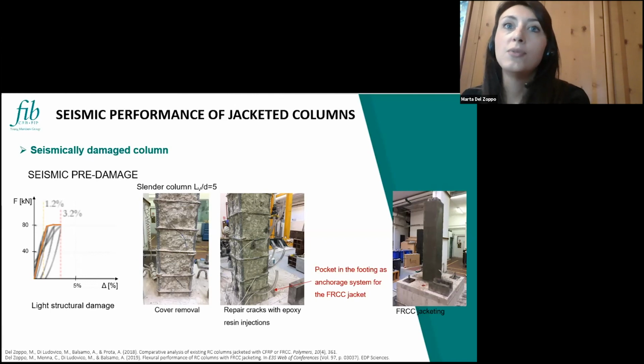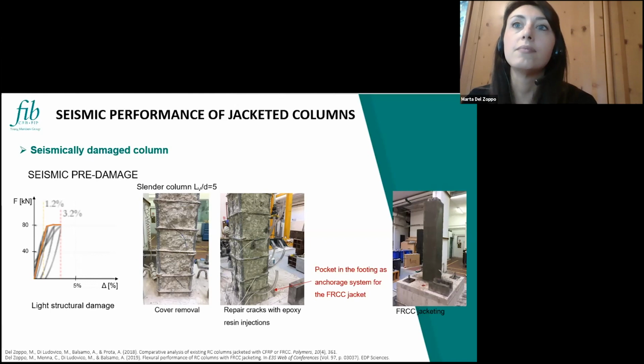So we removed the concrete cover, we repaired the cracks with the epoxy resin injection, and then we cast the jacket. In this case, we also consider possible anchorage systems to recover and try to increase also a bit the flexural capacity. We create a pocket inside the foundation block as visible in this picture, and so we cast the jacket in order to have a higher bonding surface between the jacket and the foundation.